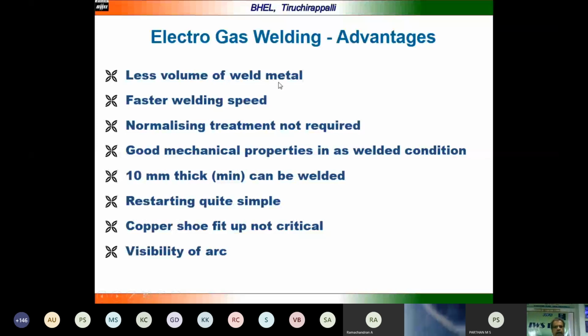When you are using electroslag welding, because of the nature of the weldment, we normally have to go for a normalizing operation, which is a post-weld heat treatment. Once you go for normalizing, the base metal sometimes may lose its fundamental properties. To avoid that, electrogas welding can be used, where there is no need of any normalizing treatment. A simple post-weld heat treatment to relieve stress is enough. Very good mechanical properties can be achieved in as-welded condition.